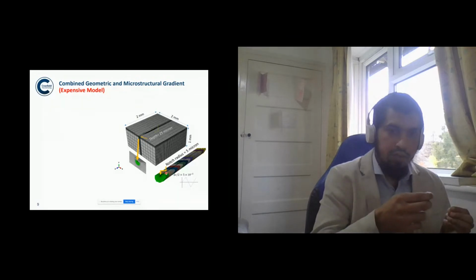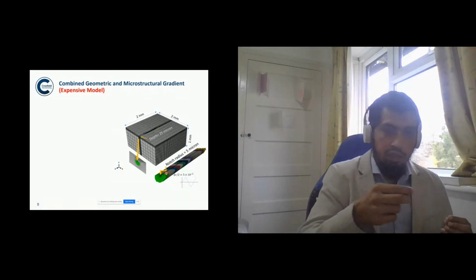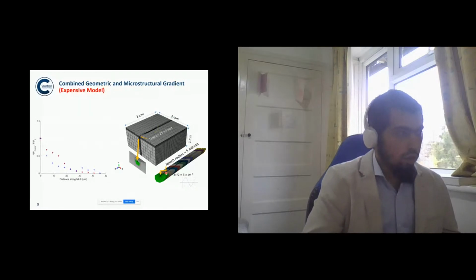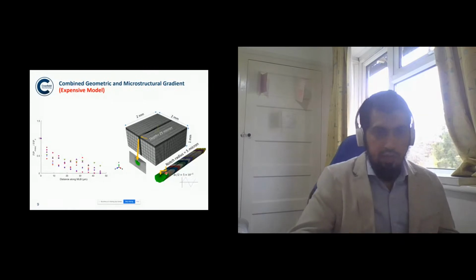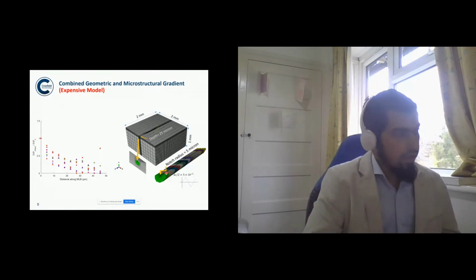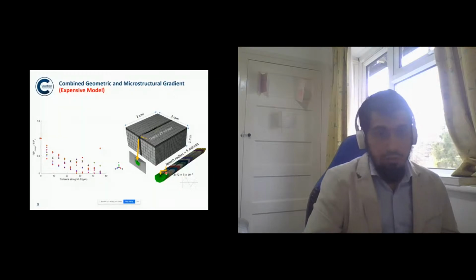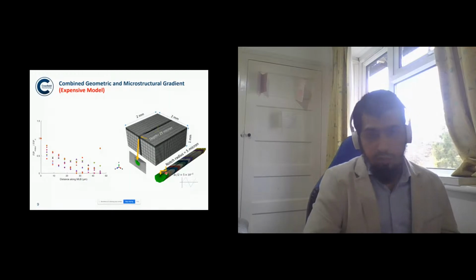So we deleted little by little the elements in the minimum life band, and we plotted the gradient of driving force as the crack extends along the minimum life band. And here we found that the gradient is much steeper. This is basically expected because we have a notch here that was not present in the previous case, where it's just the explicit microstructure. Now this really gives us the notion: can we really quantify this geometric gradient independently?